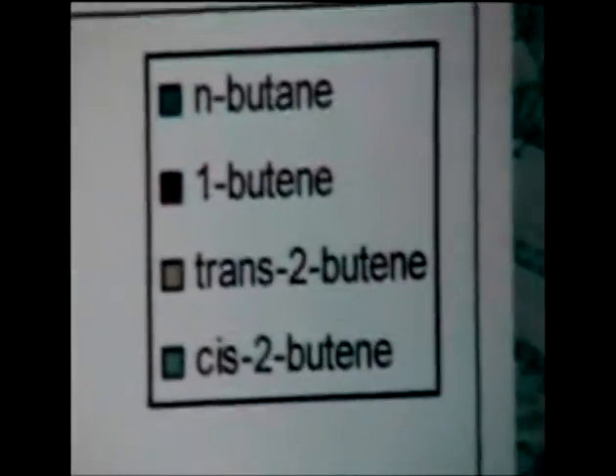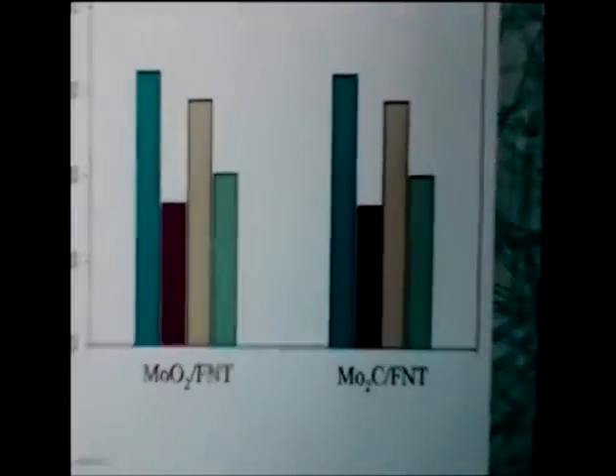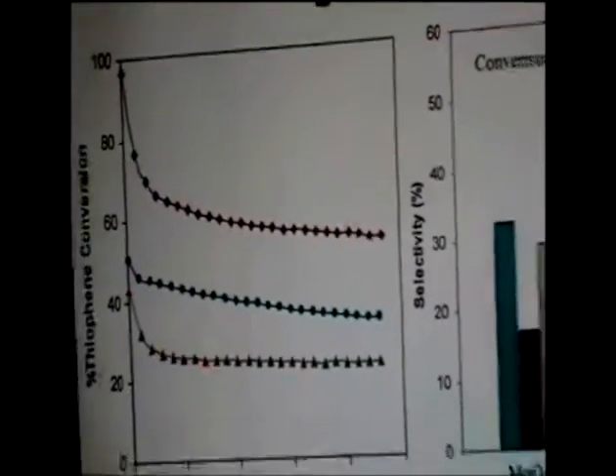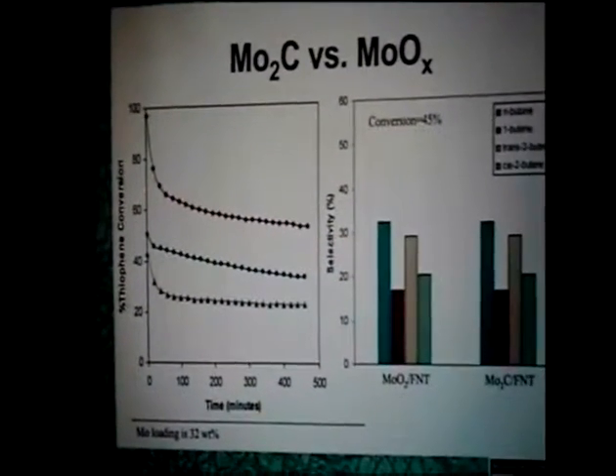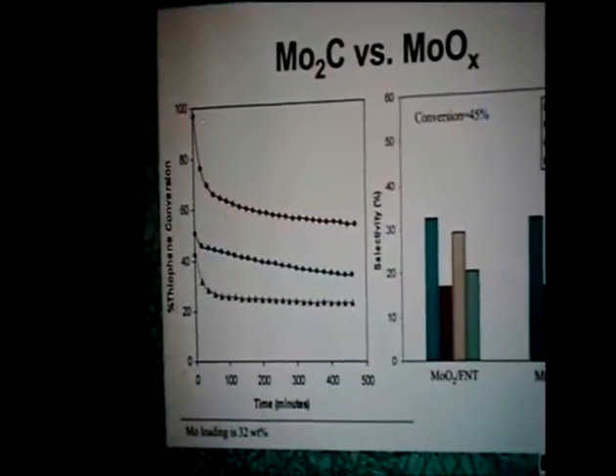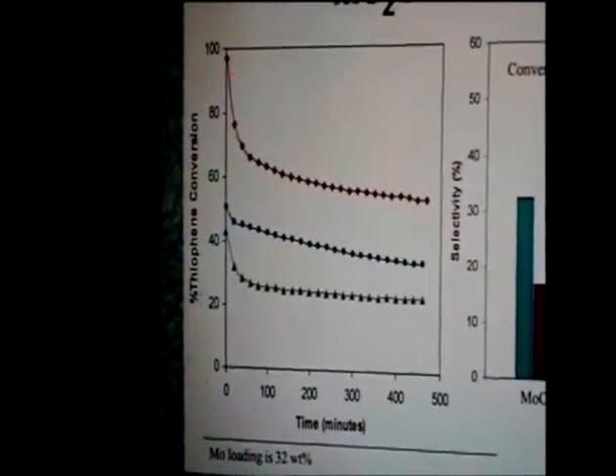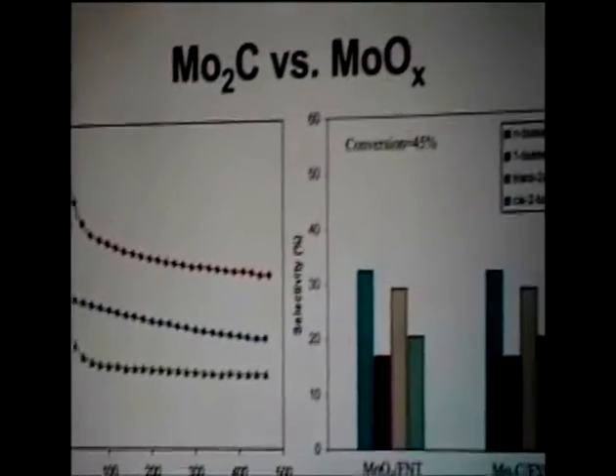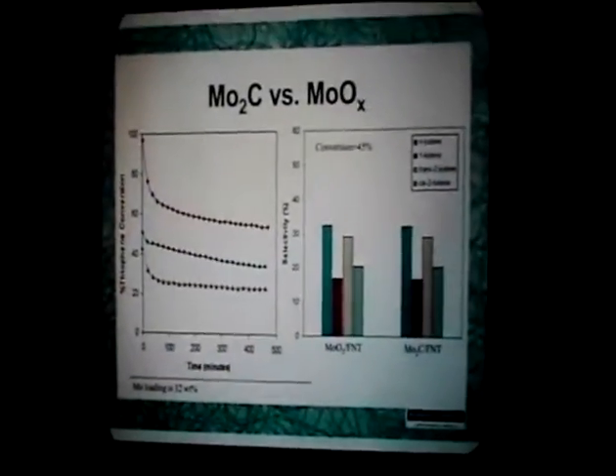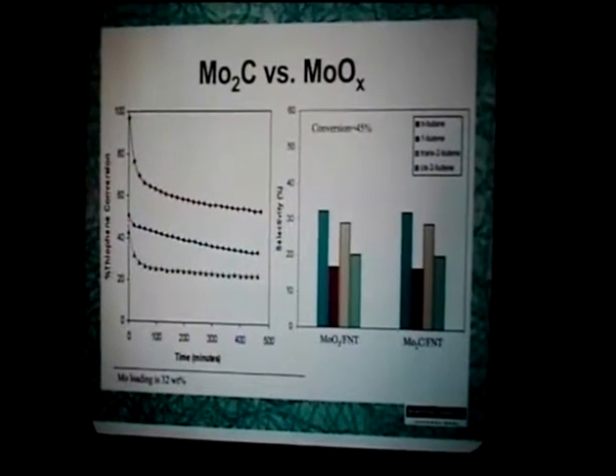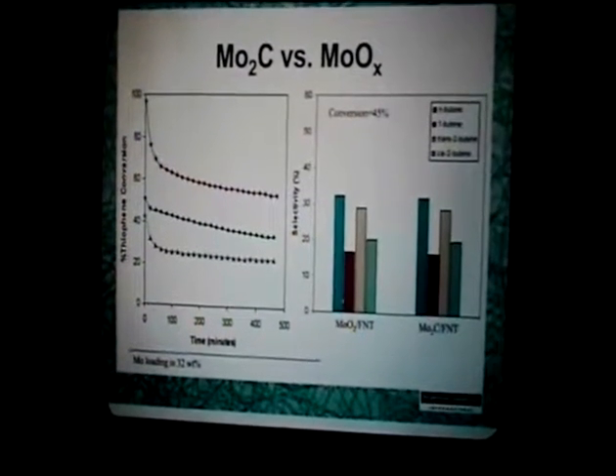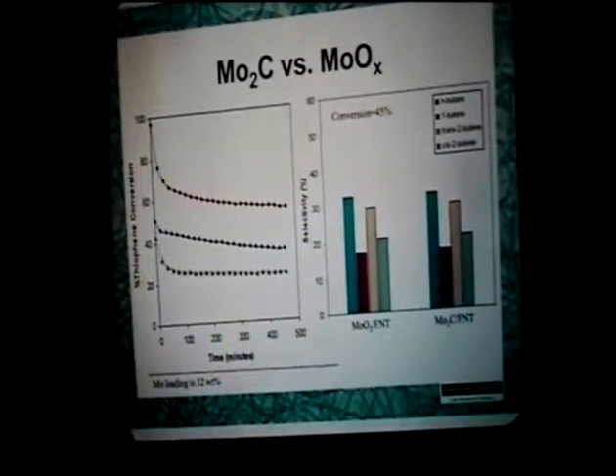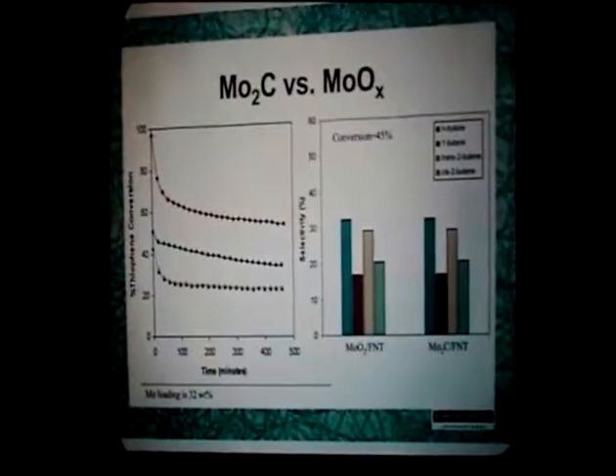We compare the molybdenum carbide versus the molybdenum oxides. I'm not sure why the printer didn't want to print here, but this is the molybdenum carbide, this is the dioxide, and here is the trioxide. So what we do in this case, we start with, again, the carbide, the dioxide and trioxide. You can see that the carbide is much more active, and the reason for that is just this active surface area. You start with the oxide, you have to form the active area first, and they also have low surface area. So you can see a much higher activity on the carbide samples, but there's very small difference on the selectivity, which means that the chemistry is all the same. But it's just a question here of surface area. We start with material with higher surface area at the beginning.